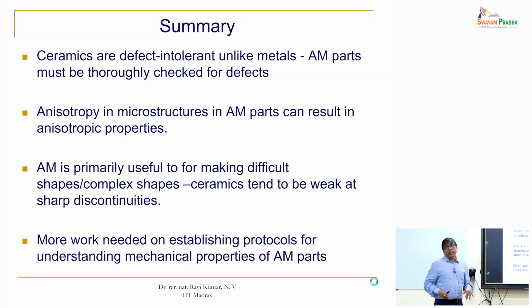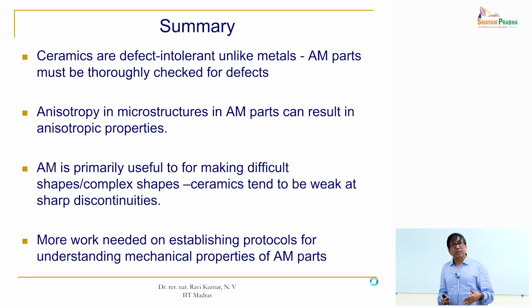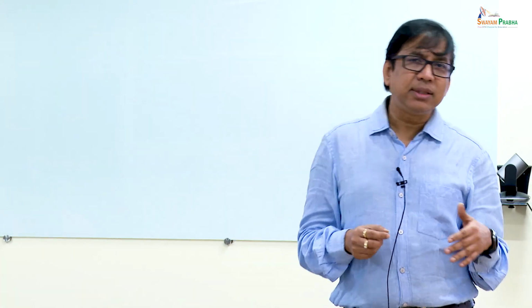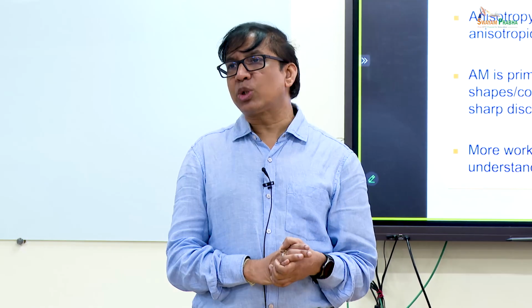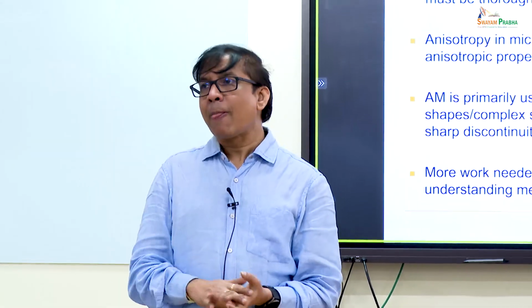And I think additive manufacturing, although in ceramics it has been in vogue for a few years, mechanical testing protocols are still not established. More tests have to be done really to believe that these are the properties and to establish them for real-time applications. So single edge notch beam, these are standards. If you look at any ASTM standard, you will know what the crack length should be. I have not mentioned it, but there are standards which clearly say what the dimensions of the specimen should be, and for that dimension of the specimen, what crack length you have to produce.